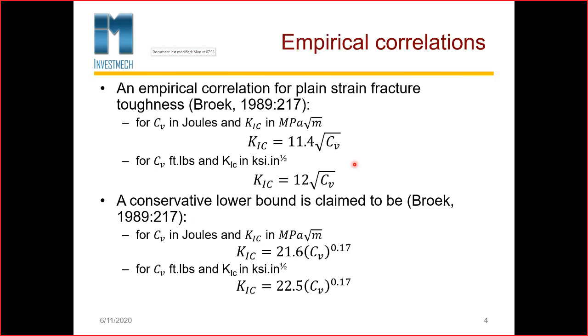There are empirical equations that you can use. The equation at the top is in joules and MPa square root meter, which is what I prefer to use. An empirical correlation for plane strain fracture toughness according to Brook is given, and the conservative lower bound was found to be a second equation. What we normally do is take the impact energy, the Charpy value, put it into these equations, and calculate the K1C values. We use the lowest value we calculate. When we want to test a potential upper bound we use one equation; the lower bound is normally given by the other.